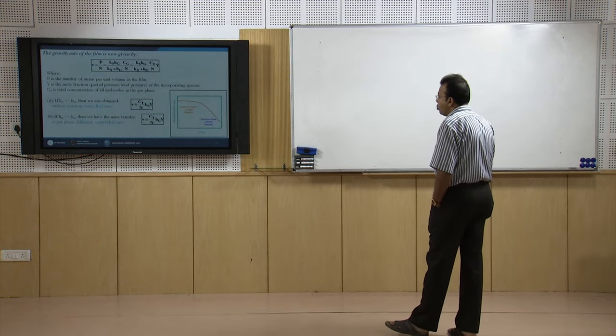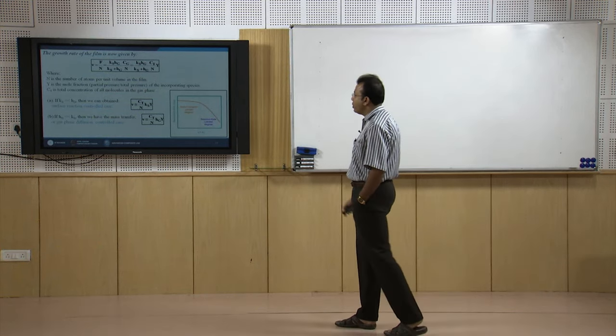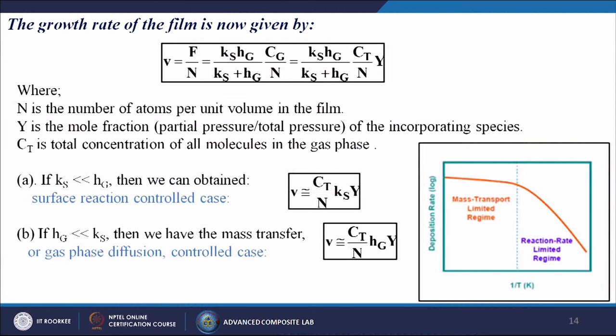Now, the growth rate of the film is given by the equation V equal to F by N, which is nothing but Ks into Hg divided by (Ks plus Hg) into Cg by N, which is nothing but Ks Hg Ct Y by (Ks plus Hg) into N, where N is the number of atoms per unit volume in the film itself, Y is the mole fraction, partial pressure by total pressure of the incorporating species, and Ct is the total concentration of all molecules in the gas phase.